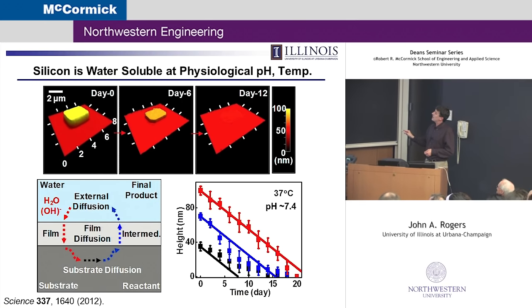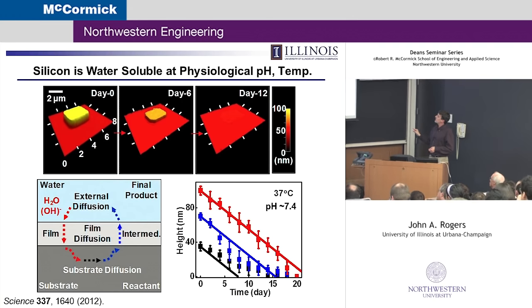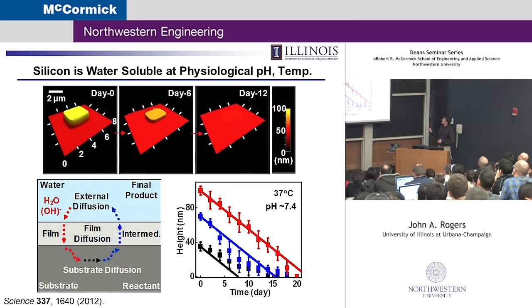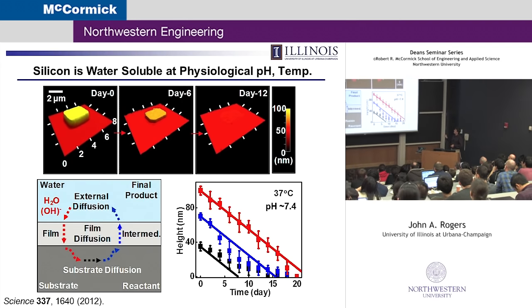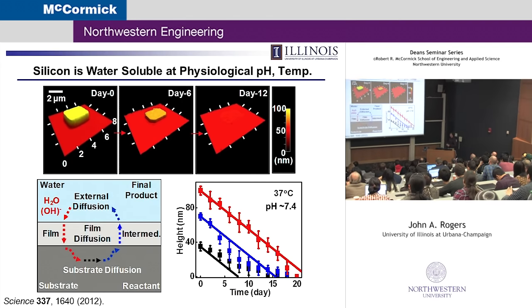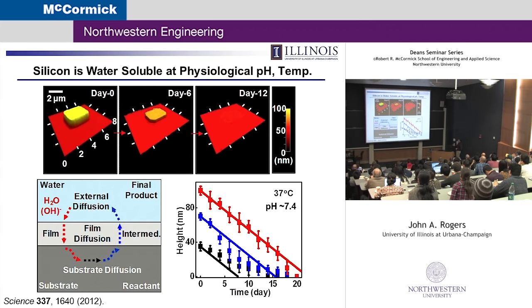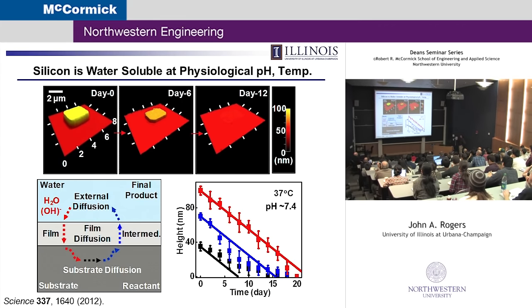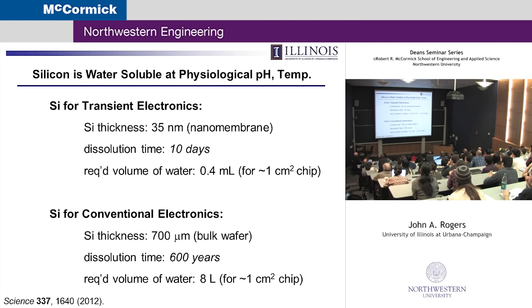So if you take one of these silicon nanomembranes, this little platelet here, you immerse it in PBS buffered to 7.4 pH, that's physiological pH, at 37 degrees, you can watch it disappear. And it disappears into reaction products of silicic acid, which is biocompatible. So there it goes. At about 2 weeks, it's completely gone. And you can map the kinetics. We work with Yonggang Huang. He does not only mechanics, but also reactive diffusion modeling to understand the corrosion process, essentially, that's governing this disappearance. But that's critical, because silicon then allows you to think about a lot of different electronic components. But let me just highlight the importance of this nanomembrane geometry.